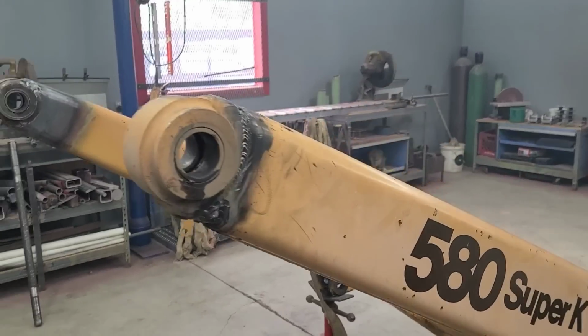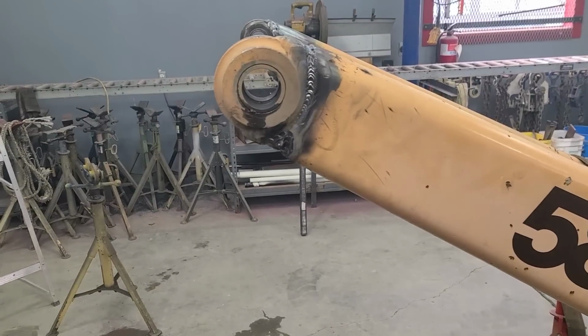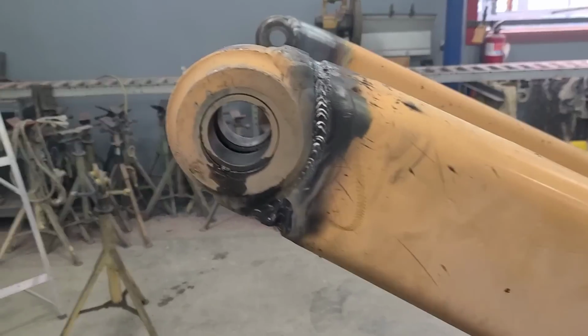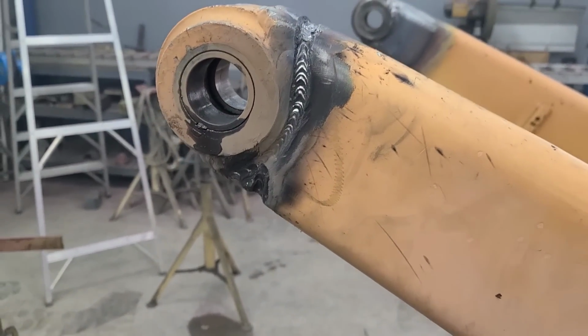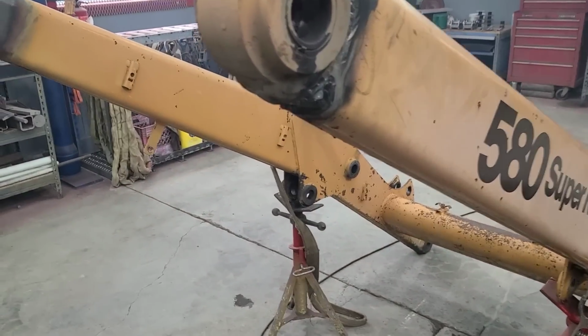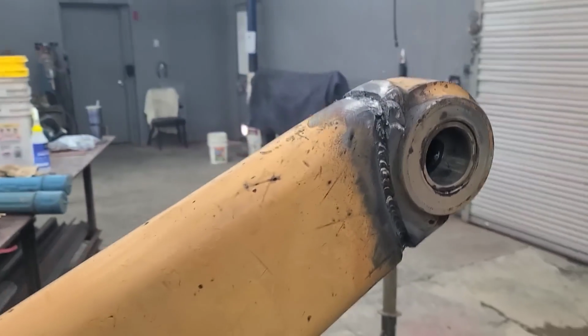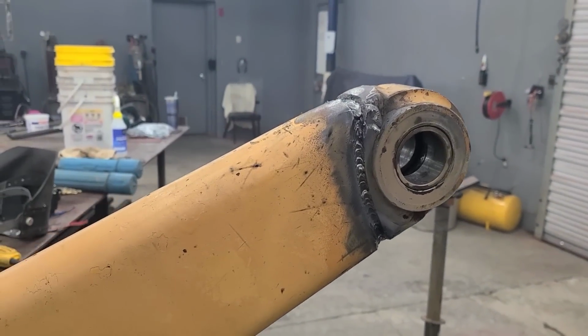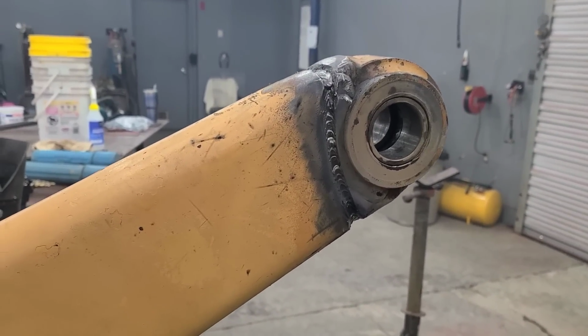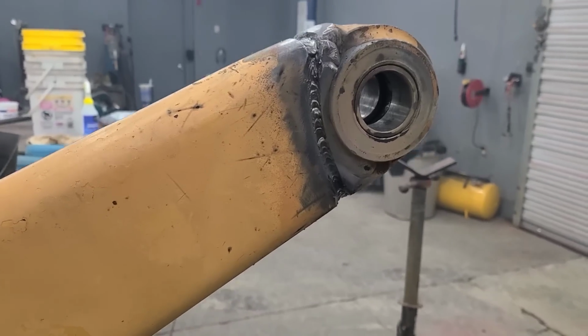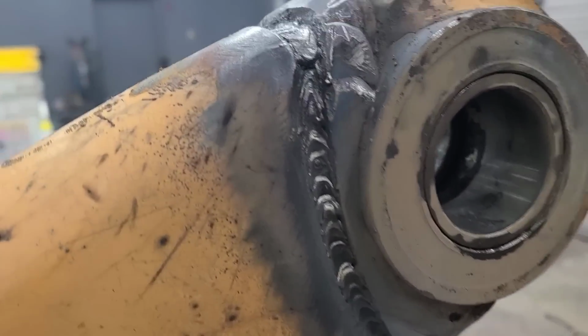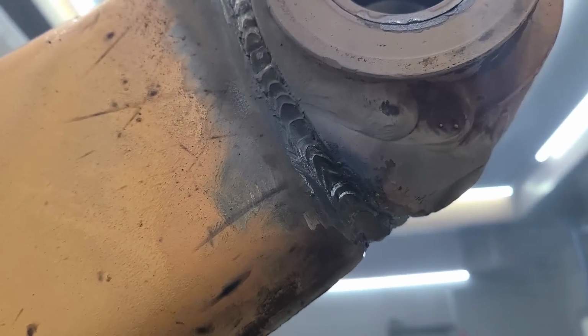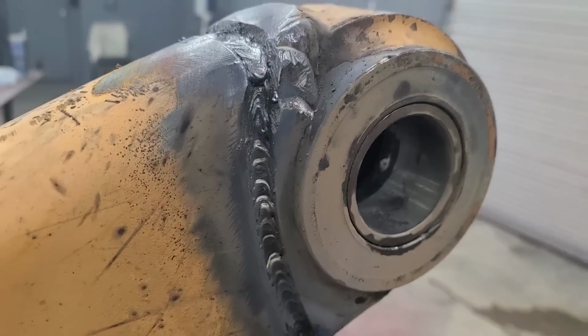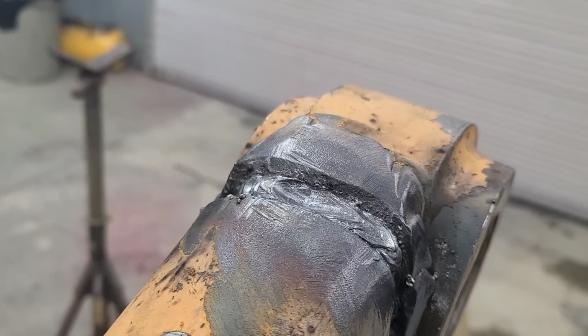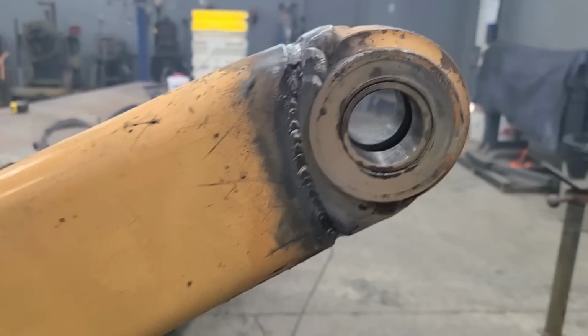So what the pipe rods allowed me to do is to run these 2 passes on here and get this thing solidified and ready to weld up without depositing too much metal. It'd be really difficult for me to have done that with the 7018, to run 2 passes and still not be full of weld. And this wasn't ready to fill full of weld. The way that I gouged it out, I want this surface that I have right here, this very deep concave surface, ready for me to weld up and put in the high quality 7018 weld.